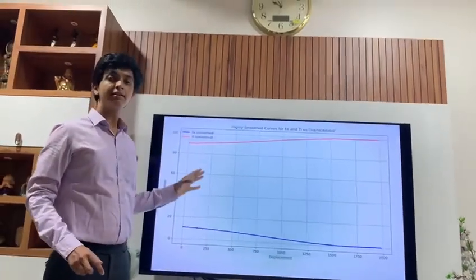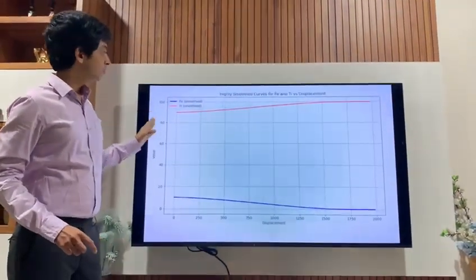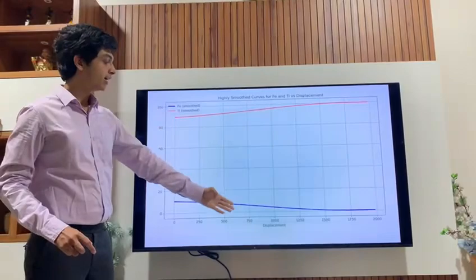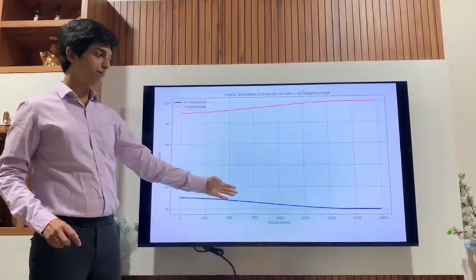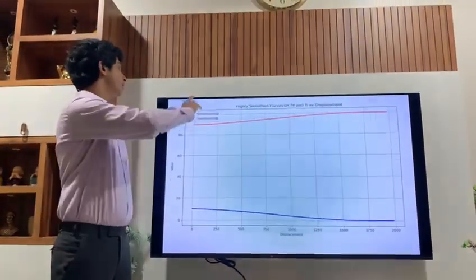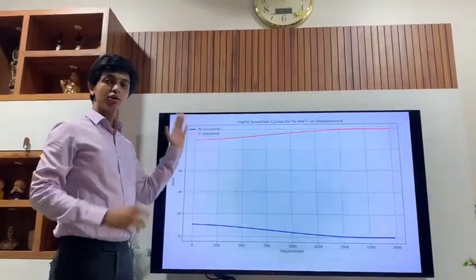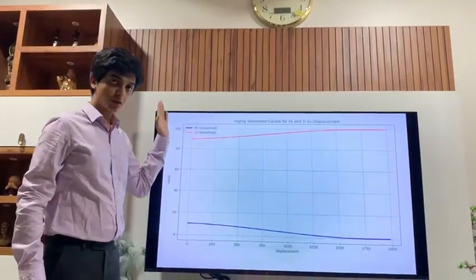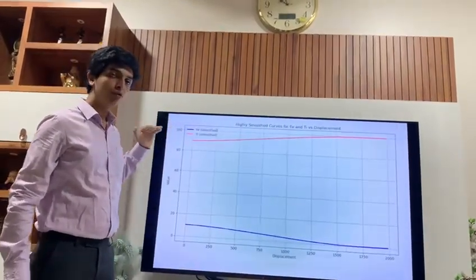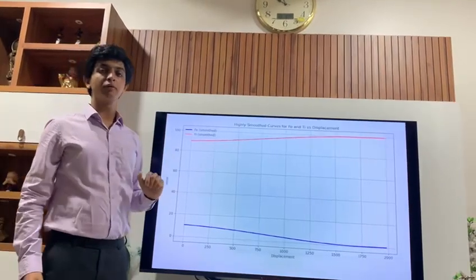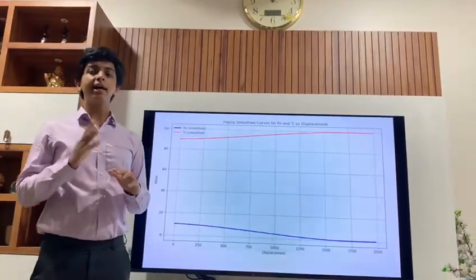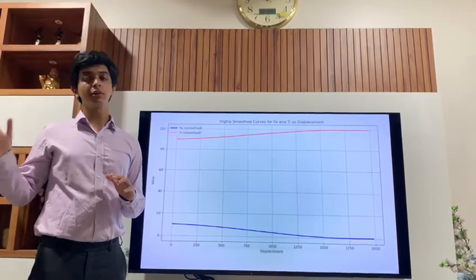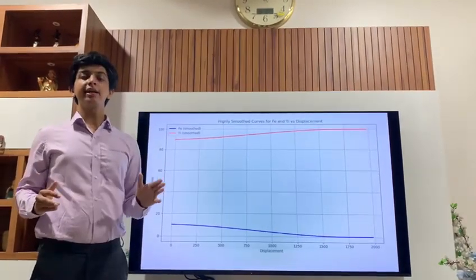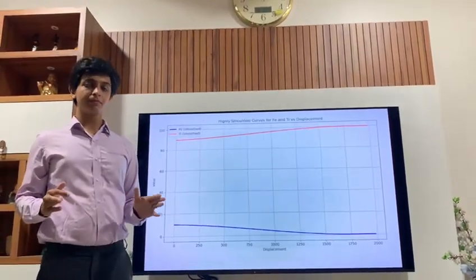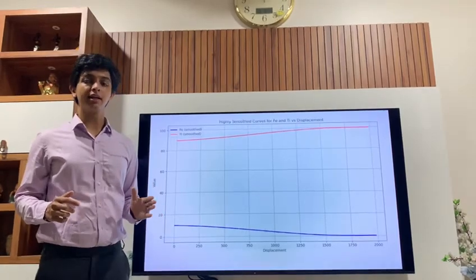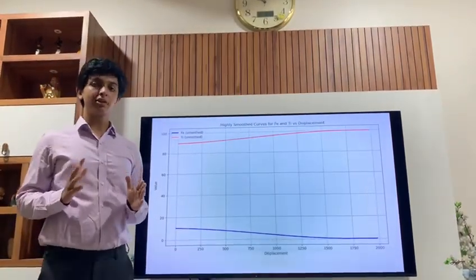This is a pretty easy graph to understand. There is atomic weight percentage on the y-axis and displacement on the x-axis. As we can see, the quantity or the value of titanium increases as we move from left to right, and the quantity of iron decreases as we move from left to right. This suggests that the iron atoms move into the titanium rich region, and the Ti atoms move into the Fe rich region. This is nothing but the Kirkendall effect, which I studied during my structural metallurgy course.